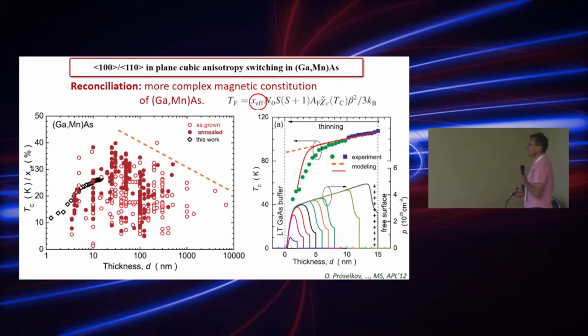That wasn't generally understood, and we provided in different studies some evidence. The evidence is the following: gallium arsenide as a material has a lot of surface states, and these surface states are predominantly donors, so they reduce the number of holes at the interface. On the other hand, this material is usually grown on a low temperature gallium arsenide buffer, which is N-type material. So we've got drainage of holes out of the material on both surfaces, with the buffer and with the free surface.